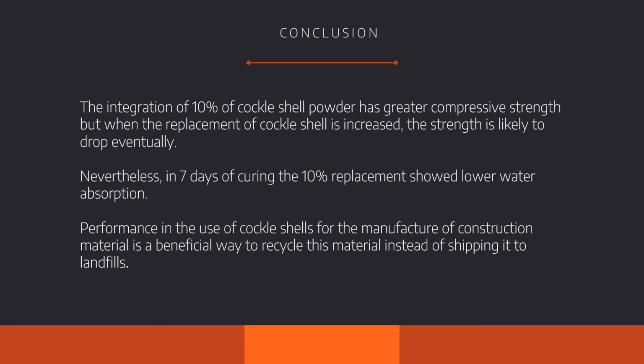Nevertheless, in 7 days of curing, the 10% replacement showed lower water absorption, and the performance in the use of cockle shell for the manufacture of construction material is a beneficial way to recycle this material instead of shipping it to landfills.